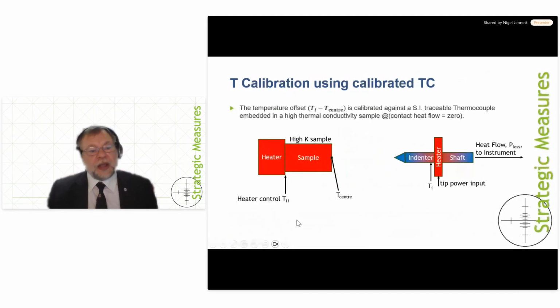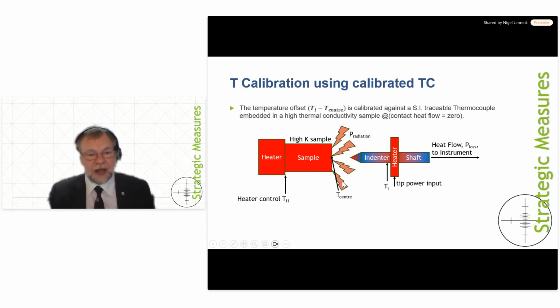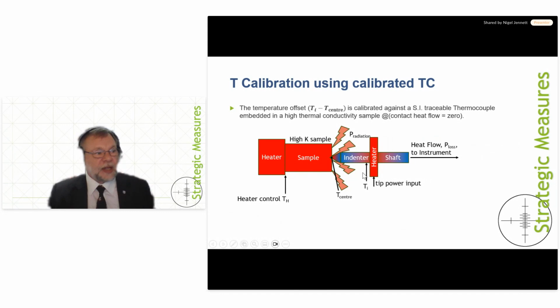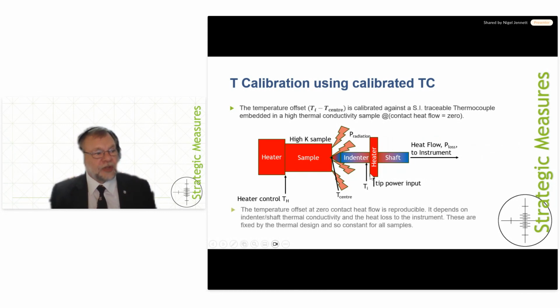So the way to calibrate that is to have a perfect sample that you can expect gives out a standard amount of radiation, so that when you indent into it, you can measure that offset. So you measure the offset when the heat flow is 0. So coming into contact, this doesn't change. That is a reproducible thermal condition. So that offset is a reproducible calibration.